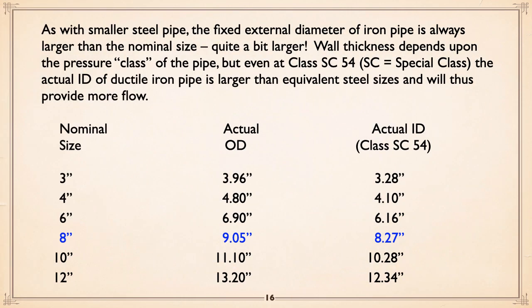Now, with ductile, the fixed external diameter of iron pipe, ductile iron pipe in almost all cases, is always larger than the nominal size, quite a bit larger. Wall thickness depends on the pressure class, but even at SC54, special class 54, the actual ID of the ductile iron pipe is larger than equivalent steel pipes and will thus provide more flow. For example, you can see